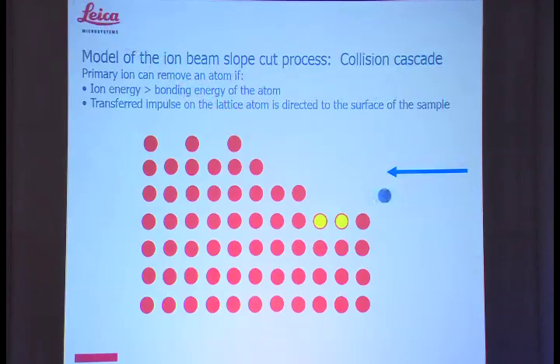So it's called broad ion beam milling compared to focused ion beam milling, because here we can produce a 1/4 millimeter area of sample. So very, very big in comparison to FIB.